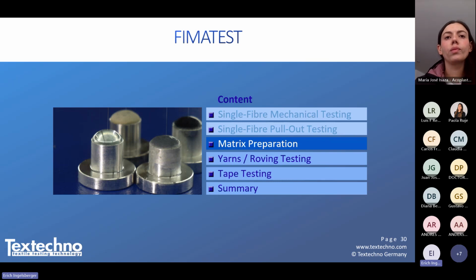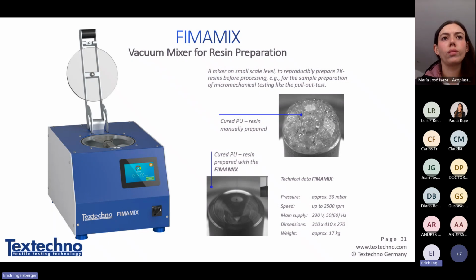Just very briefly, matrix preparation. What could happen if you prepare the matrix, especially polyurethane matrices, manually, is that you will have a certain bubble effect, because the matrix still contains some humidity. So manual mixing can result in bubbles, which of course will falsify the pull-out testing results.